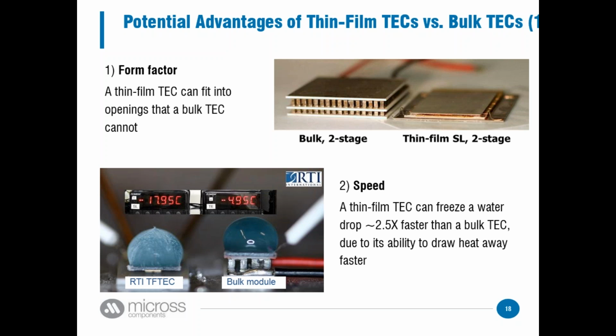And this photo you have here is from an experiment I did back in one of my DARPA projects. Essentially what I did was take two modules, a thin film thermoelectric, which I built, and a bulk thermoelectric module, put a drop of water on each one, and then basically turned on the power. What we essentially saw was that the thin film thermoelectric module froze that drop of water in about 15 seconds. The bulk thermoelectric module froze it in about 48 seconds. So just the speed at which the heat can be pulled away is a big asset compared to what you would get in a bulk module.